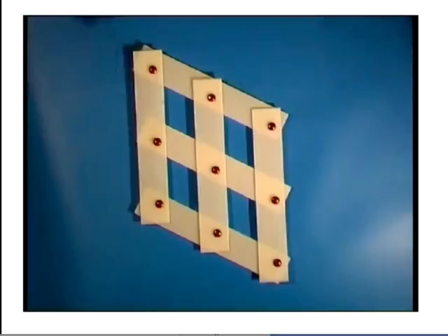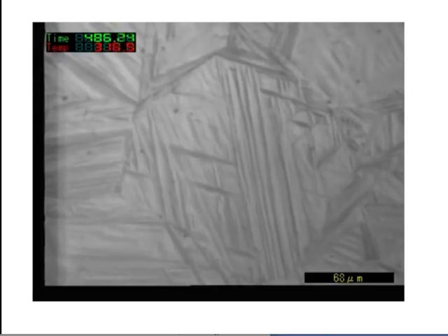And if we polish austenite completely flat and then allow it to transform to martensite, we should see this happening. In the next slide, this is a movie by Koseki in Japan, where we are looking at a flat surface of austenite. These are austenite grains, and we allow it to transform into martensite, and you'll see exactly that sort of change happening. Those are martensite plates forming, which are tilting the surface. There's no etching here. We are just seeing the surface relief forming. So this is a real physical deformation, exactly like slip, except that we are changing the crystal structure at the same time. You should think of martensitic transformation as a deformation which changes the crystal structure at the same time.